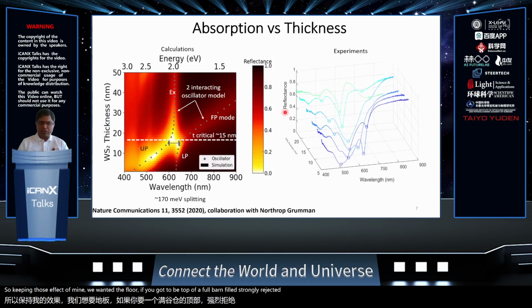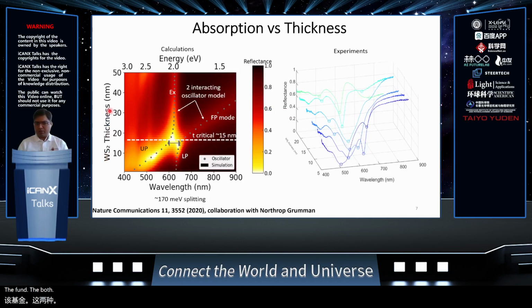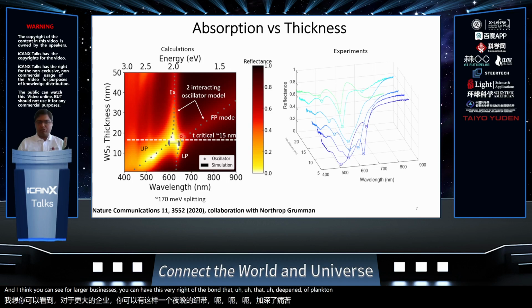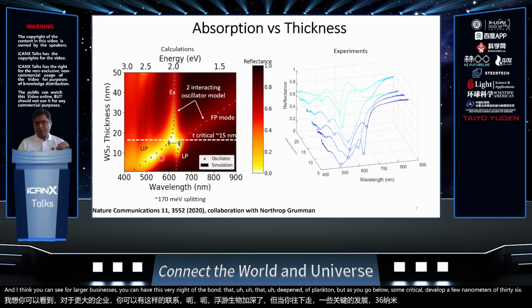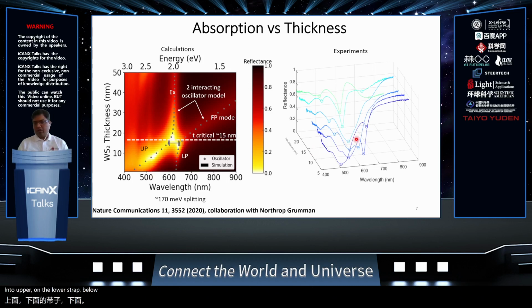So we did these experiments where we varied the thickness of tungsten disulfide. Tungsten disulfide is the choice material over here because it has a very nice exciton at about 2 eV or so. And as you can see, for larger thicknesses, you can have this very nice exciton dip in reflectance. But as you go below some critical thickness of 15 nanometers or so, these peaks split into upper and lower exciton-polaritons. You can see these extremely well in experiments too, where the peaks are very nicely split.